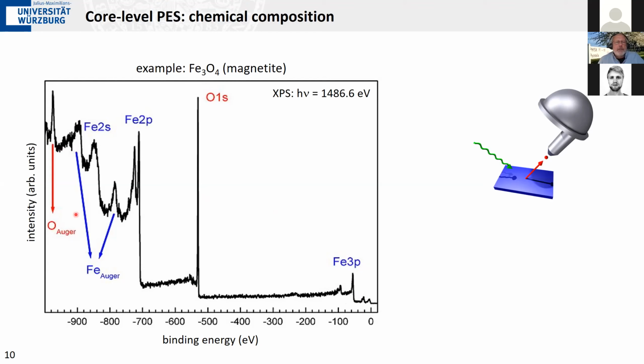These are Auger electrons. When you excite electrons from the core levels, you create core level holes. And these holes can decay again by Auger processes. So electrons from higher occupied core levels can fill this core hole. Energy gets released by that and can be absorbed by other core electrons, which will then be excited into the vacuum. So these are not photoelectrons, these are Auger electrons, but they are part of the spectrum that you measure.